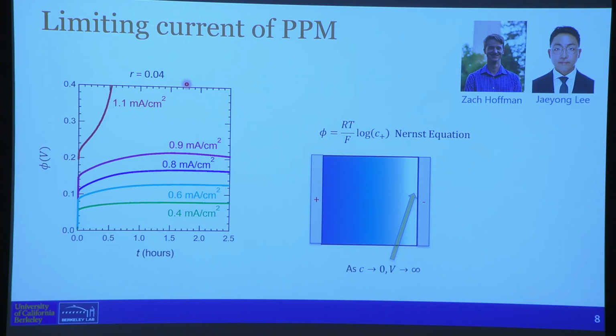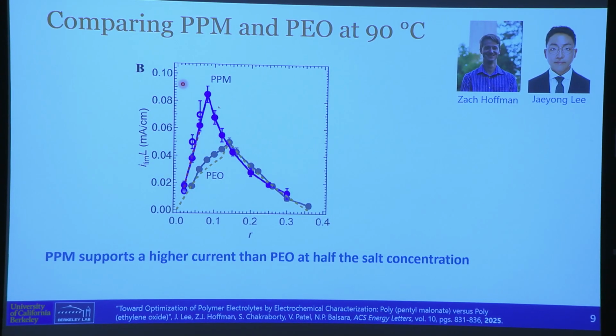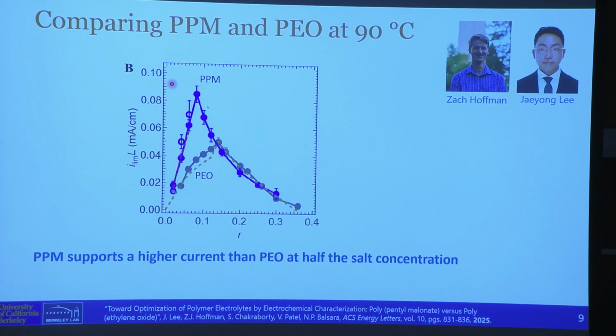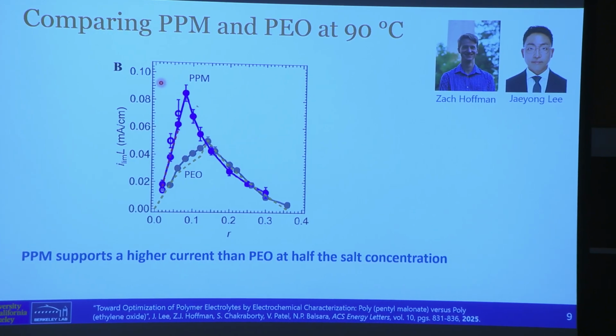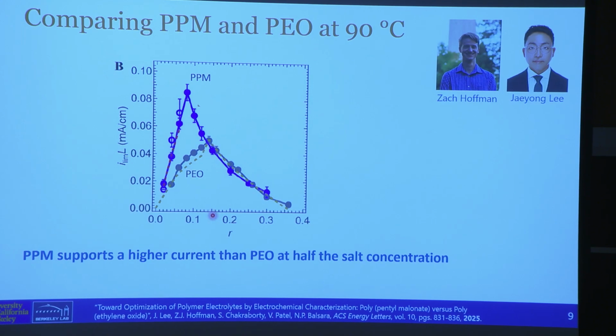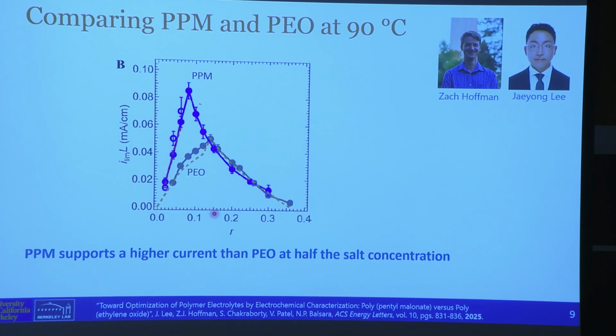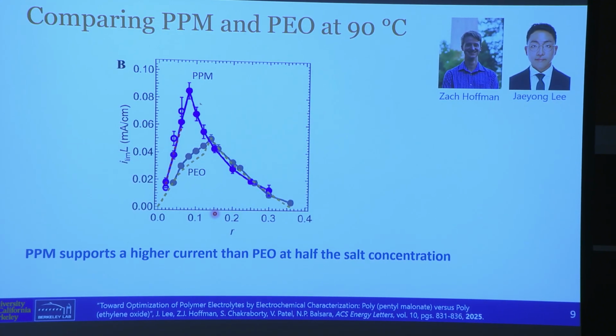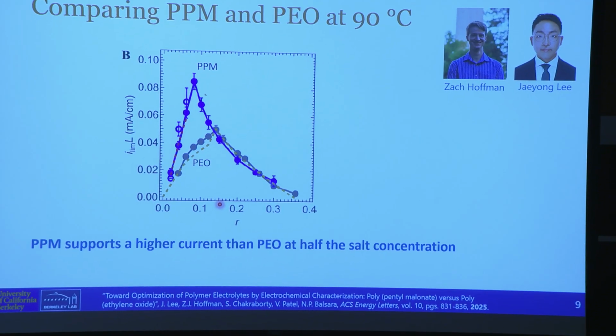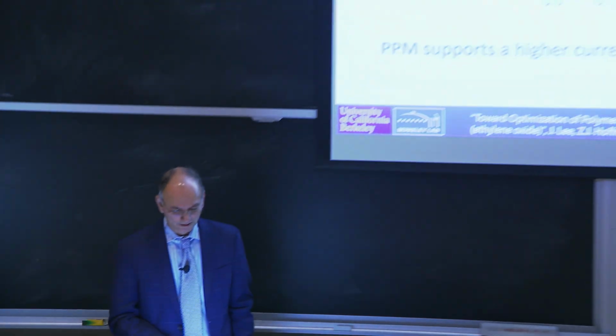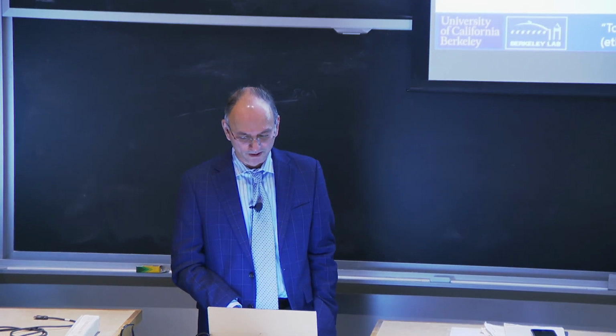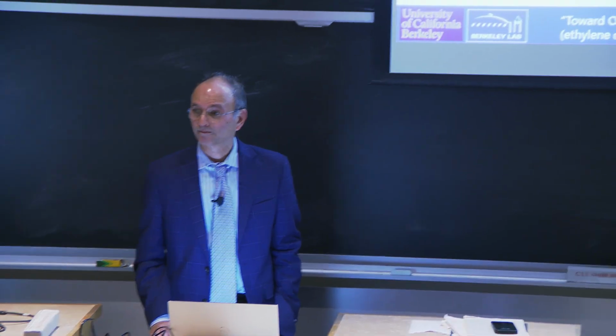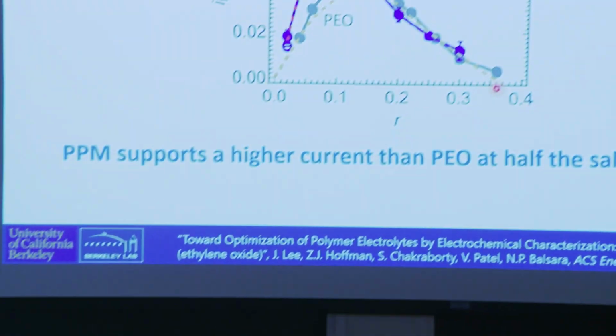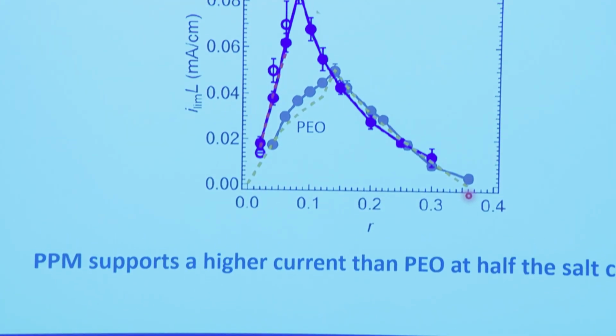We did that at different salt concentrations. We, I mean Zach and Jaeyong. And here are the data as a function of concentration. The limiting current on the y-axis is a function of concentration on the x-axis. In spite of the importance of limiting current, this is the only data set I know of limiting current as a function of salt concentration from the dilute limit all the way up to the concentrated limit. I would love to know of any other system where this has been measured.